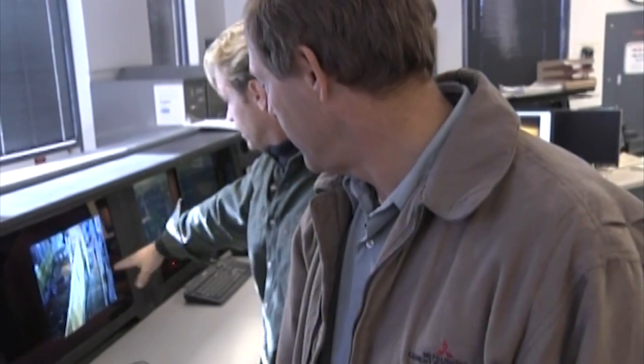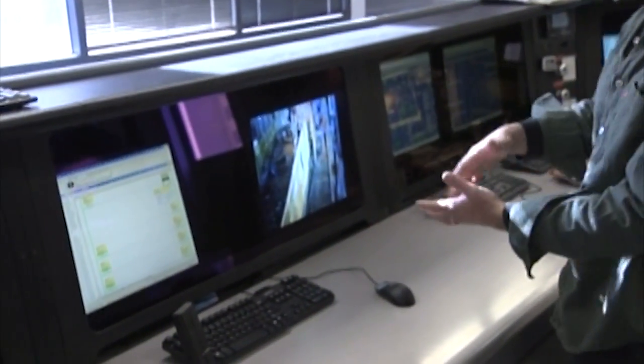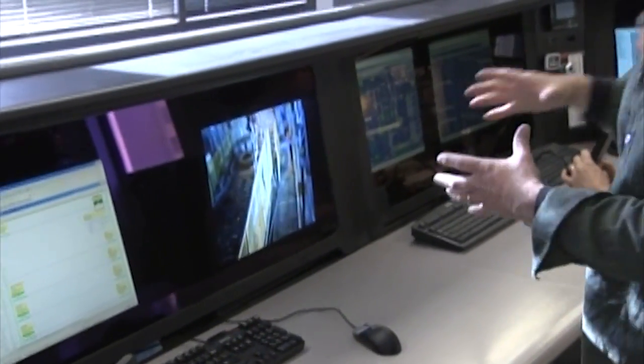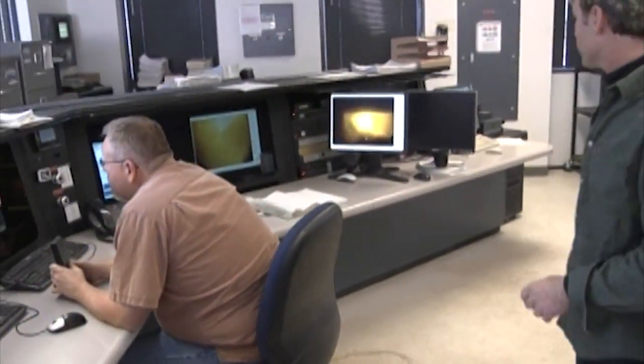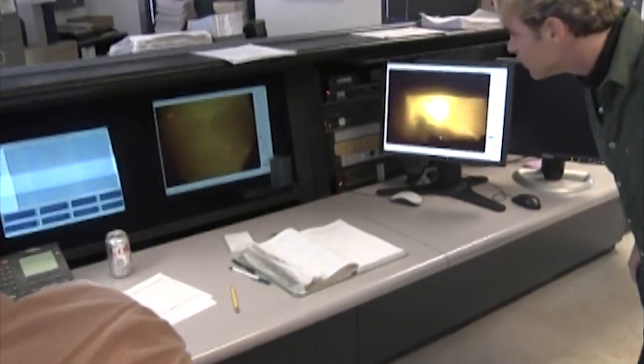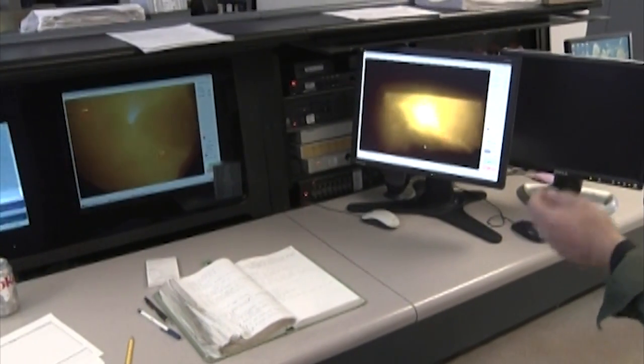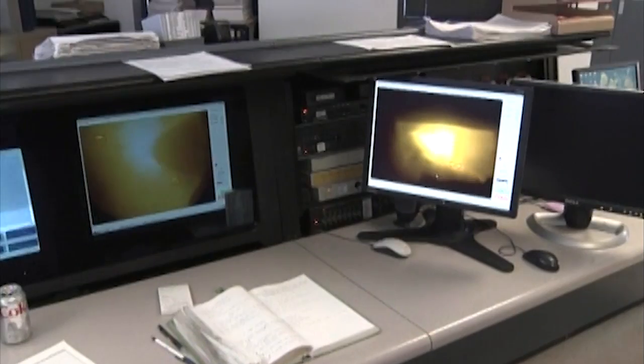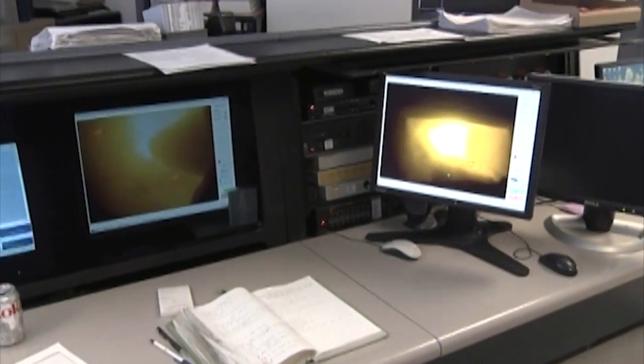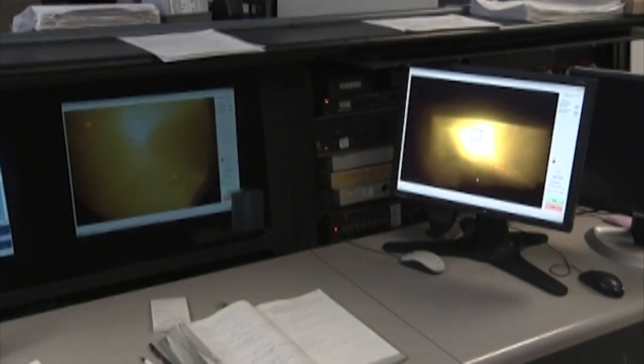On the screens I can see the tires making their drop in. And over here is the big flame. We have two cameras looking at high-temperature locations. The one on the left is the coal flame at the nose of the kiln — we watch to make sure it looks like a nice uniform flame. On the right is looking at the hot clinker dropping into the clinker cooler, dropping out of the kiln at 2,800 degrees into the first stage of cooling.